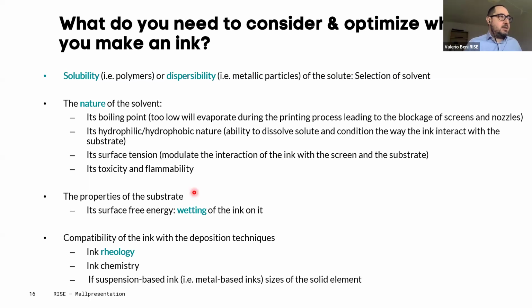One aspect that I didn't mention, and I apologize for this one, especially when it comes to inkjet printing and aerosol jet printing, you have limitation in terms of the physical size of the particles, when we talk about particles present in the inks. So usually you need to be of the order of few hundreds nanometers. Otherwise, you will have a high chance or risk to clog, so basically block the nozzle or block the output of the inks. So these are all aspects that need to be considered in the manufacturing of inks.